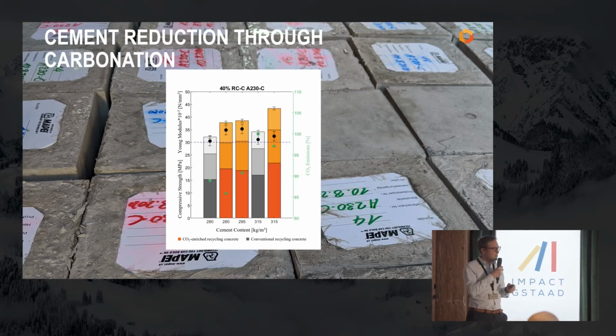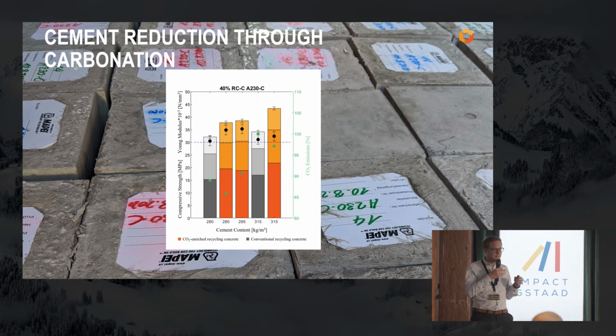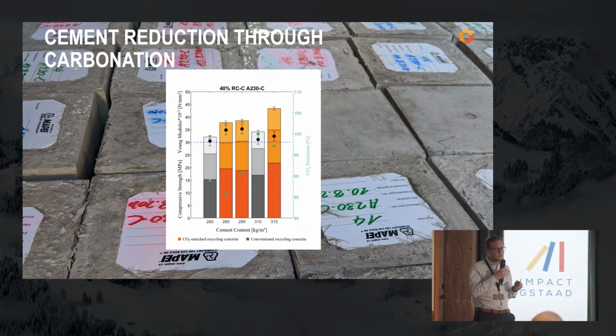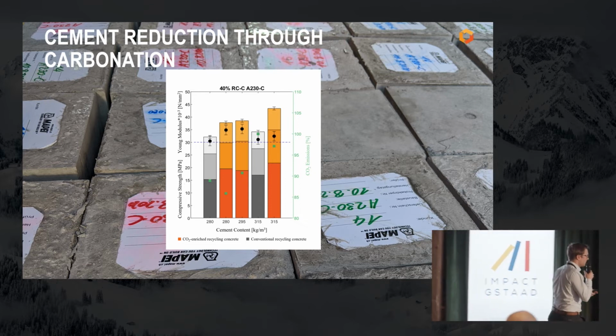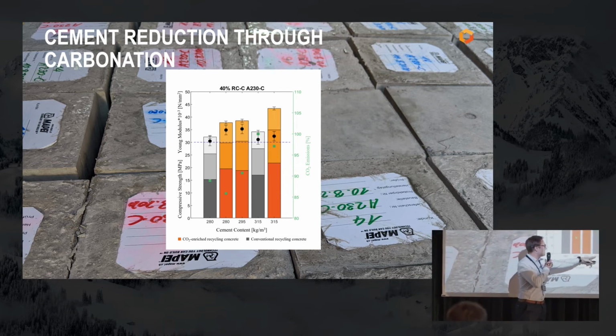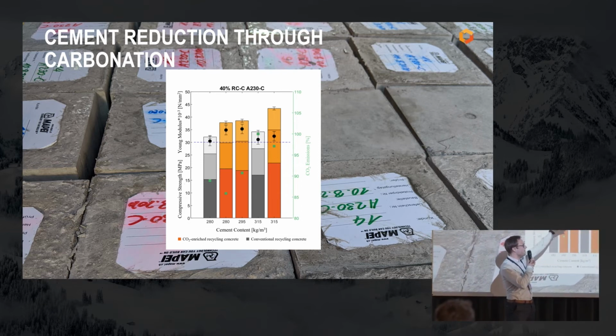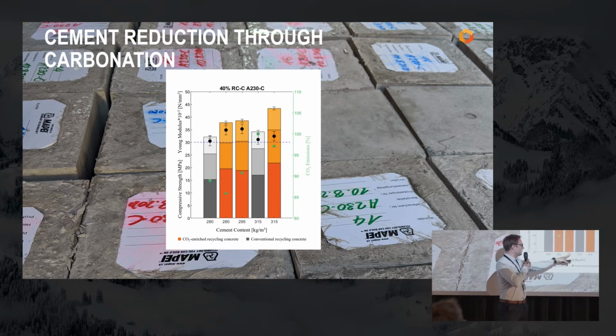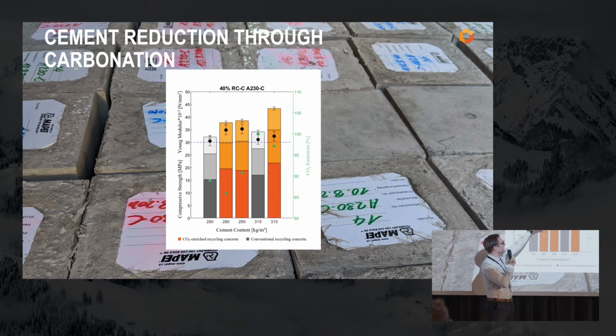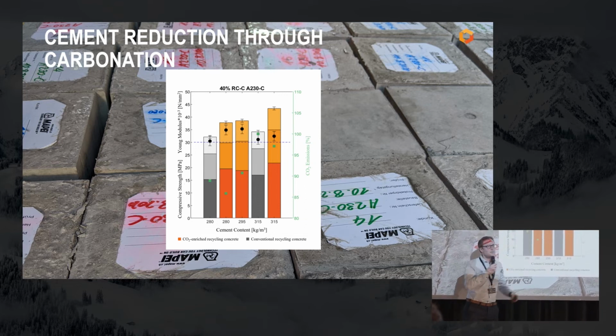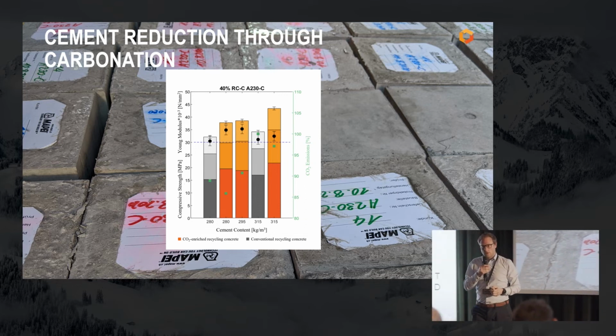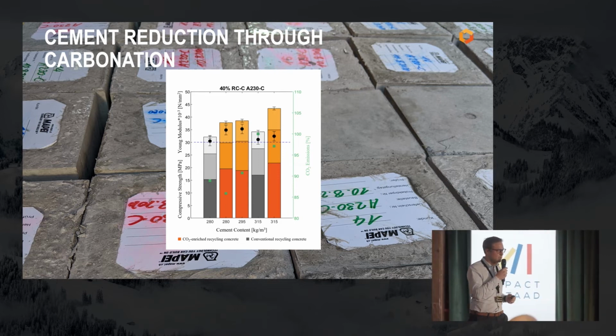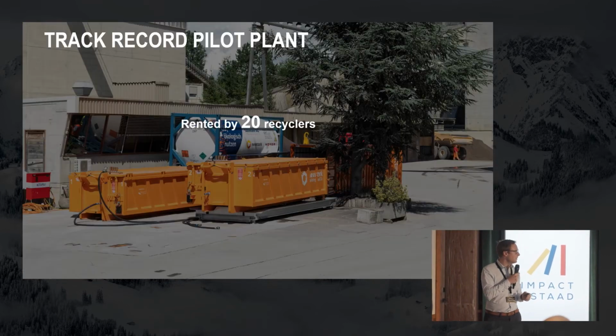In addition, we also tested what happens if we use the material in concrete mix designs. And what you can see here is basically a reference concrete mix design with the compressive strength indicated by the bar. And if we take the same mix design but reduce the cement content and carbonate the material, we can get, let's say, even better properties at lower greenhouse gas emissions. So this is indeed very promising.